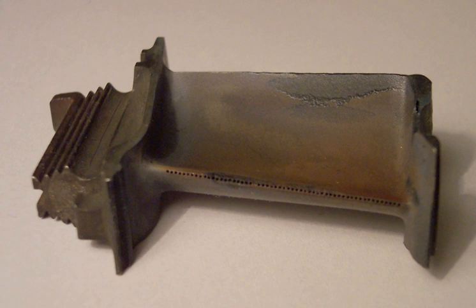By this mechanism, the yield strength of gamma phase Ni3Al actually increases with temperature up to about 1000 degrees Celsius, giving superalloys their currently unrivaled high temperature strength. Initial material selection for blade applications in gas turbine engines included alloys like the Nimonic series alloys in the 1940s. The early Nimonic series incorporated gamma Ni3Al(Ti) precipitates in a gamma matrix, as well as various metal carbides, e.g. Cr23C6 at the grain boundaries for additional grain boundary strength.